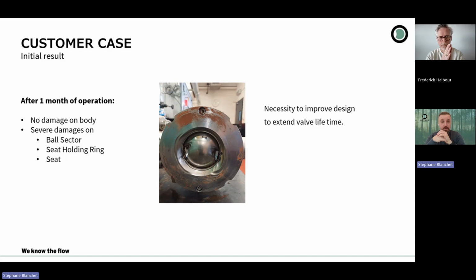So we were thinking, okay, what can we do in that case? We know that there is obviously ceramic valve in the market, so why can't we make this kind of ball sector valve with a ball sector covering some parts in ceramic to increase the hardness, to make sure that it improves the lifetime? And then we were thinking, okay, we can do that, of course, but then obviously the cost and the availability will be much worse. I mean, the cost will be very high, and it would also take very long to produce this type of valve. So we were thinking outside the box and to see what other coating alternatives we can do. Because at the end, the idea was to increase as much as possible the hardness, to make sure that we can fight as much as possible the abrasion. Because to make sure there is no abrasion, we want to have a material which is as hard as possible.